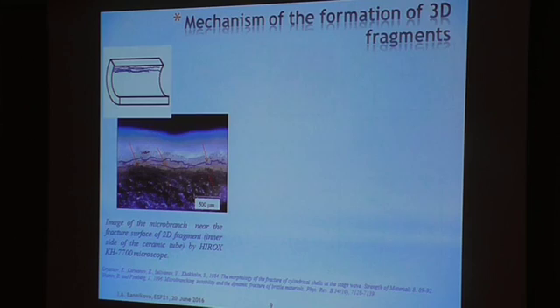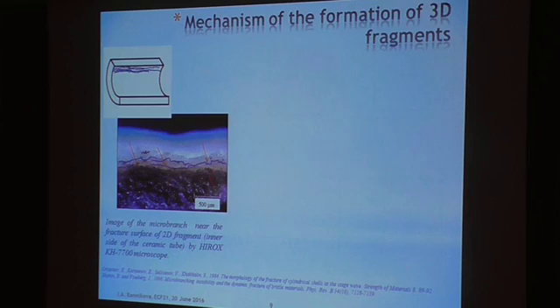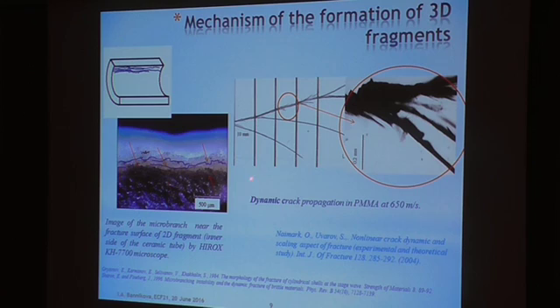This is an image of the microbranch near the fracture surface of 2D fragments on the inner side of the ceramic tube. The same dynamic crack propagation was obtained in this laboratory and in the simulation.